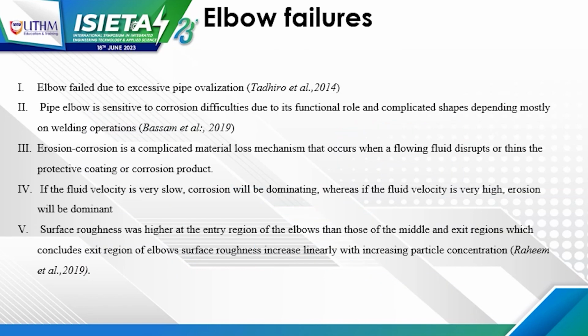Elbows normally fail due to excessive pipe ovalization and also sensitive corrosion difficulties due to their functional role and complicated shapes depending mostly on welding operation. Erosion and corrosion is a complicated material loss mechanism that always occurs due to flowing fluid disruption. This is why the elbow is the most critical part compared to other fittings or other parts of a pipeline. When the fluid velocity is very slow, corrosion will dominate. When the fluid velocity is very high, erosion will be dominant. And a study by Rahim says the surface roughness was higher at the entry region of the elbow than at the middle and the exit region.